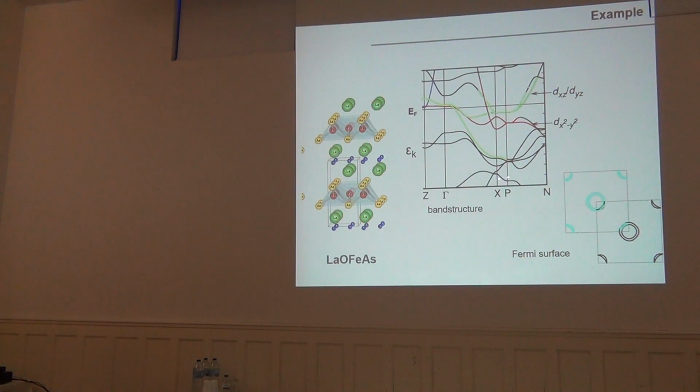Okay, so now here I'm showing the Fermi surface. I just did this cut and looked at what is empty, and these would be empty pockets, which are these ones here, so we call them hole pockets. Now I just go along the gamma X path, and I'm going into these electron pockets, and what it's telling me is that I have a strong dispersion here, which is what I was expecting, because I'm moving along this path.